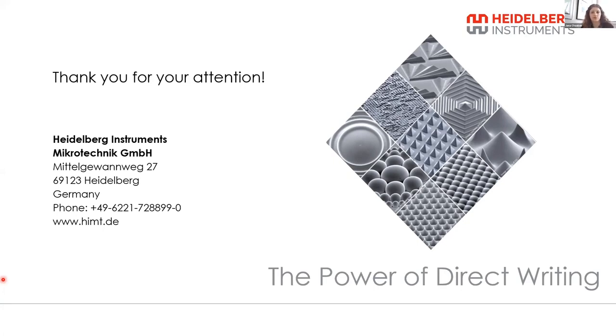But also going back to your initial question, for the NanoFrazor, the field that we pattern is 50 by 50 micrometers. And if you want to pattern larger areas, then you need to stitch 50 by 50 micrometer fields. But actually, we have an integrated algorithm for the stitching. In this case, we use the AFM mode to scan the existing patterned field and stitch it to the next field that we would like to pattern. And so we can do that with an error of less than 50 nanometers.